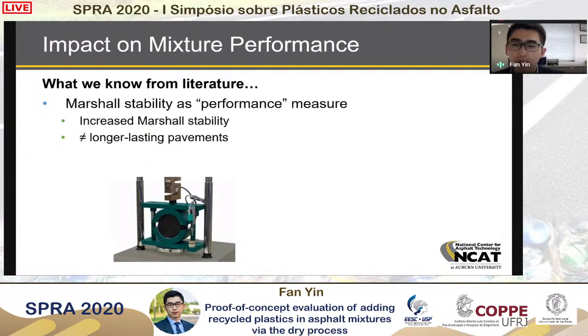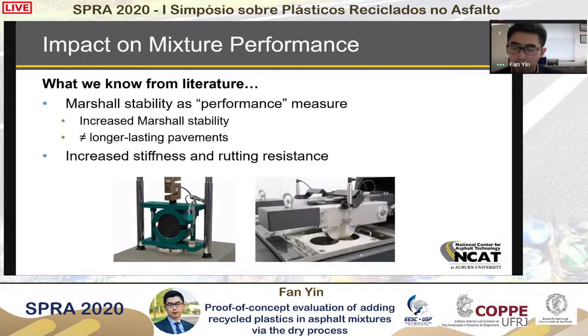But we know this kind of conclusion may not be well supported because, first of all, based on the research that we have done over the last 20 to 30 years with Marshall stability, we know there's not a really good correlation between Marshall stability and the rutting resistance in the field. Even if there's a good relationship there, one thing that has not been considered is the cracking performance. Right now in the US, cracking is the primary form of distress in asphalt pavements. So we definitely need to address the durability and cracking resistance of the mixture to be able to make our pavement last longer. There is quite a bit of research done to look at the stiffness and the rutting resistance, and they all show a positive impact from adding recycled plastic on those properties.